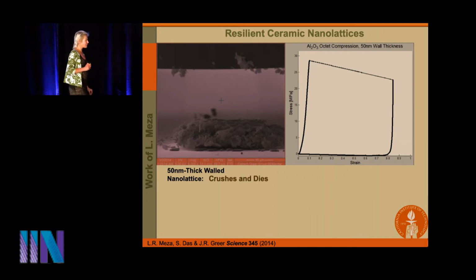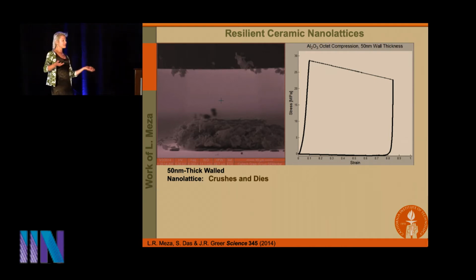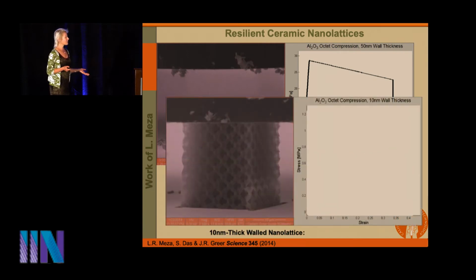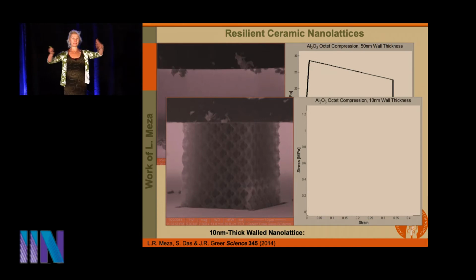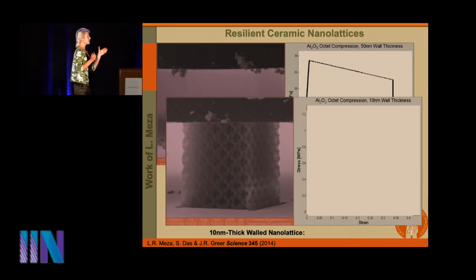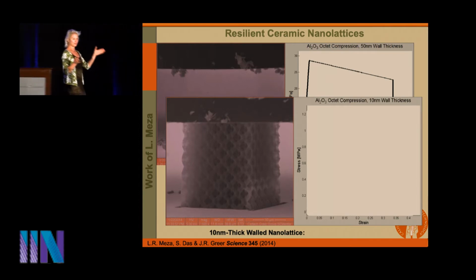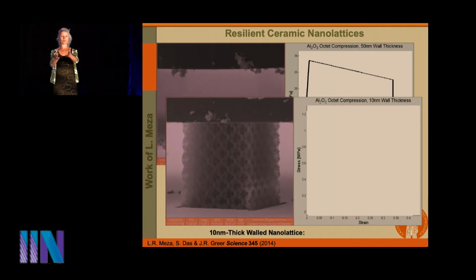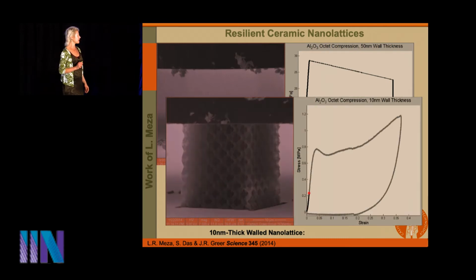Now, all right, it remained strong, but it didn't do anything else interesting. So we repeat this experiment in the following way. We keep everything the same: the same geometry, the same material, the same microstructure. The only thing that's different now is we're reducing the wall thickness by a factor of 5. So now instead of 50 nanometer walls, we're going to have 10 nanometer walls. Same alumina, very, very brittle, even more brittle now, right? So we're going to compress it. We should experience the same behavior.